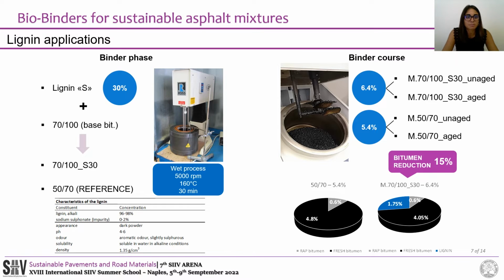Then the same binders were employed to produce asphalt mixture for binder course. Both mixtures were characterized by the same aggregate gradation, including 15% of RAP, while the binder content was optimized based on volumetric considerations. In the end, the use of the biobinder resulted in a 15% reduction of bitumen in the mixture.